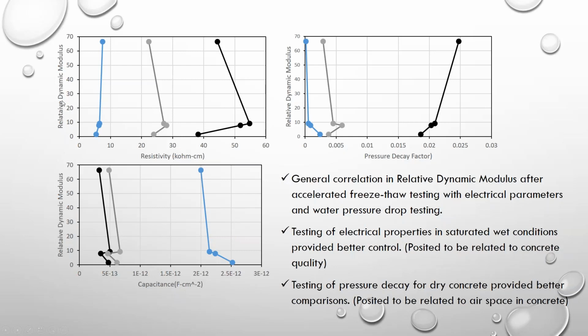This relative dynamic modulus is actually saying how much of the strength of the concrete is lost after the freeze thaw, accelerated freeze thaw testing. So the higher number, the more resilience it has to its attack. So at least for electrical testing, we can look at the blue lines. The blue lines represent conditions where the concrete was soaked, so the pores were saturated.